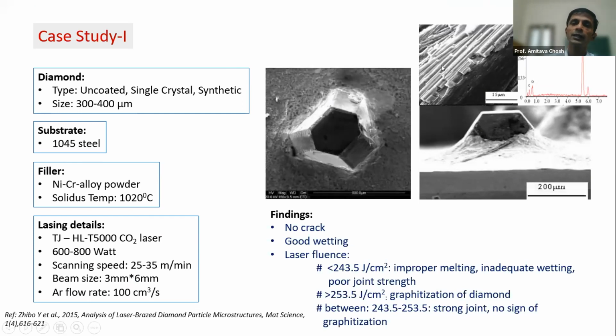The same metallurgical reaction, because chromium as an active element makes chromium carbide at the interface and makes the appreciable wetting take place. But some of the salient observations show that the laser fluence, basically a specific energy, is the laser peak power multiplied by the pulse width, divided by the beam area.